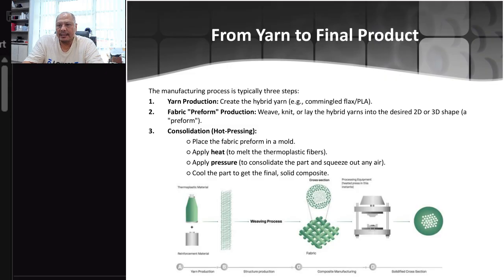The second is fabric preform production, like weaving, knitting, or laying the hybrid yarn into the desired 2D or 3D shape preform. After that, number 3 is consolidation by hot pressing. You can see on the right side, they put the fabric preform in a mold, apply heat to melt the thermoplastic fiber, apply pressure, and then cool the part to get a final solid composite. You see in the picture: yarn production, structure production, composite manufacturing, and then the solid cross section or final product.